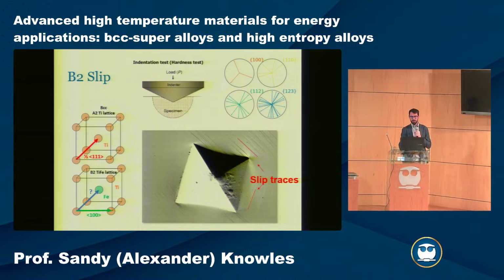And what we noted is that at the corner of the indents, you quite often see these slip steps. These are steps that are formed from the passage of dislocations. And they have a very characteristic orientation. You always see them in very specific orientations around the indent. And the question we had is, if you then know the orientation of the crystal underneath that indent, presumably the slip traces are tied to the slip planes that are active in the material. And if you know the slip planes, you then also know the Burgers vector. So you might be able to work out and screen for ductility just using hardness and EBSD, rather than having to go to TEM.